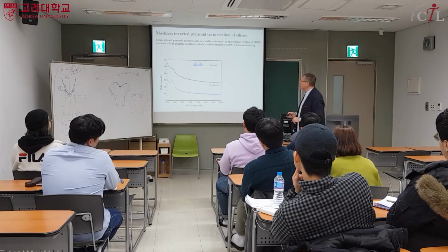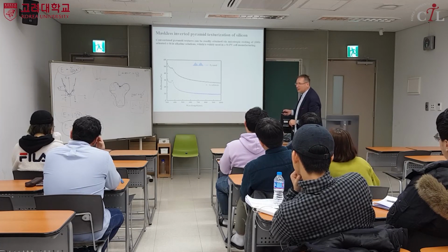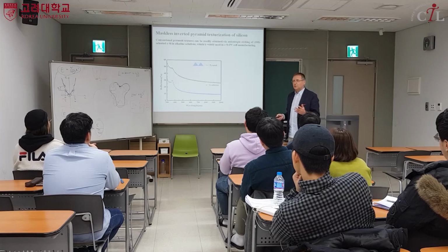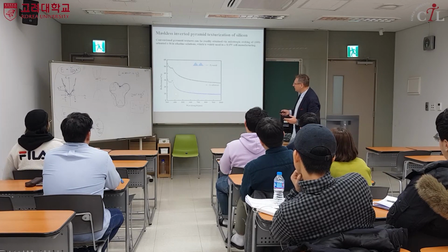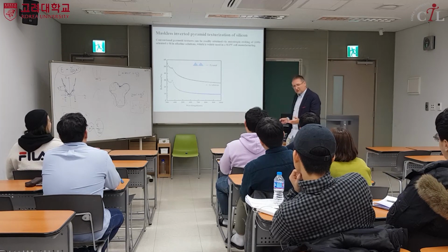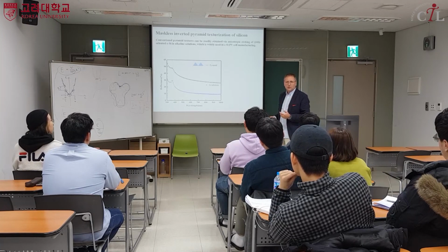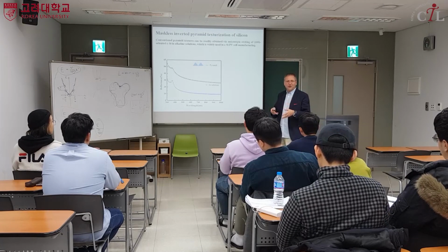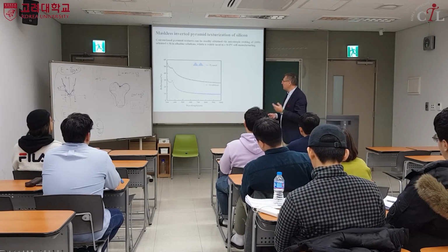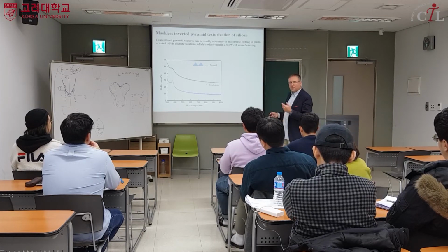This is done in a KOH solution. But still, you see, a lot of light is reflected. Maybe 10% of light is reflected. It's a lot. It's a lot of loss. How do we get better absorption and less reflection? There are methods. There is even a material called black silicon. Maybe some of you heard about that. It doesn't reflect anything, but it is so bad. It's really very difficult to make junctions on that. So basically the clue is we need texture like that, but that would reflect less.